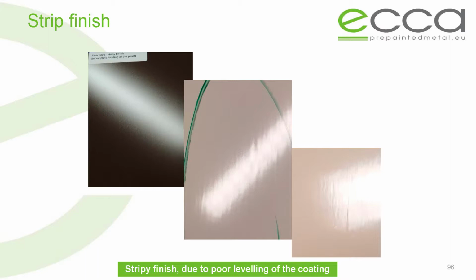You can improve the flow of a coating by reducing that coating surface tension. There's all kinds of ways to reduce that coating surface tension. But the problem we have on a coil line is, if you form this ropiness, it's maybe 2 seconds before the coil goes into the oven, and 5 seconds later you've lost maybe half of the solvent, so now your viscosity is so high that you almost don't have a prayer of smoothing that out. So we'll talk about surface tension in just a bit.